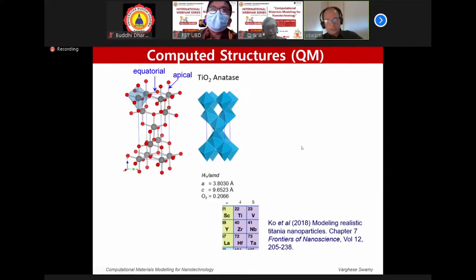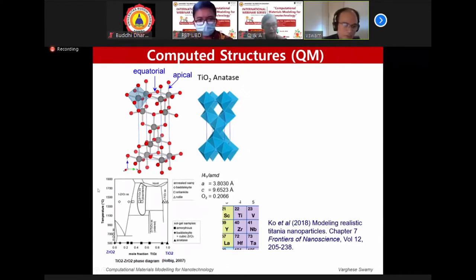Now, I talked about zirconium earlier. If you look at the periodic table, titanium, zirconium, hafnium are all group 4 metals. So you might think zirconium can also form a similar structure to titanium when it forms the oxide. But if you look at the phase diagram shown here, that's not the case. Here, the binary phase diagram of zirconium dioxide and titanium dioxide is shown. You can see that at low temperatures, you start with anatase. It's not heated or anything. Anatase is the starting material. If you put some zirconium in it, it can take up some zirconium in the anatase structure.